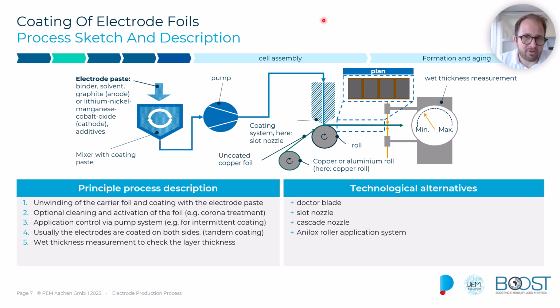So we have coating speeds of 35 meters per minute, which can be even up to 80 meters per minute in the industry. And of course, here we are creating the throughput of the whole line, as this is a very crucial and very highly controlled process. Here you set the quality of the battery for all the later stages. So from here on it can only get worse. So you want to make sure that your coating process is really good, and that the combination of your mixing, the secret formula, the secret ingredients for your battery, is really transformed well onto the electrodes. And those two processes are, I think, the most crucial ones in battery production quality-wise.